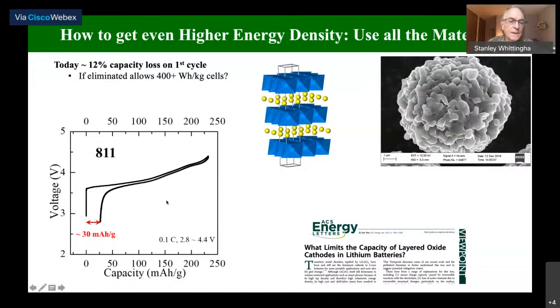If we actually look at the cycling of these materials, on the very first cycle, we charge them. Here's the charging cycle. This is up to about 4.4 volts. And then discharge follows very nicely. But then we have what's called the first cycle loss. This is between 10 and 15% of the capacity, and you never get this back again. So we're losing this 30 milliampere hours right from the beginning. If we want to get a higher energy density, we need to recover this.